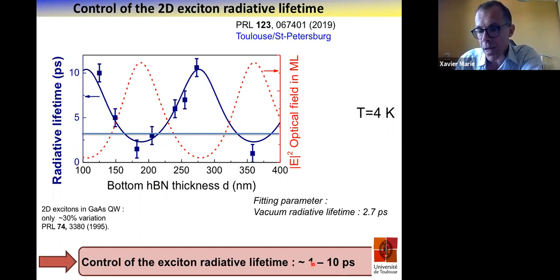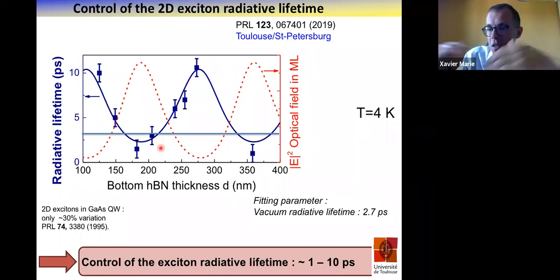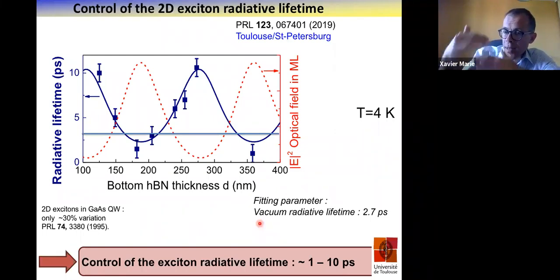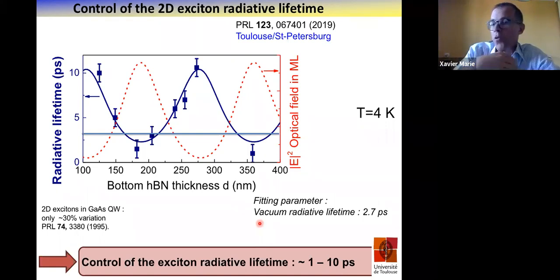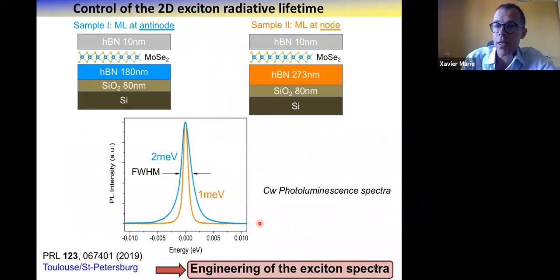And we can vary the time by one order of magnitude, typically between 1 and 10 picoseconds. So it's mainly the inhibition of the radiative recombination time and a little bit of enhancement. The enhancement factor is small because we use this very bad mirror, but the effect is here. So we have now, thanks to the controlled dielectric environment, exciton lines almost governed by the radiative recombination, not fully governed. You still have some inhomogeneous broadening, but the main mechanism is the radiative recombination.